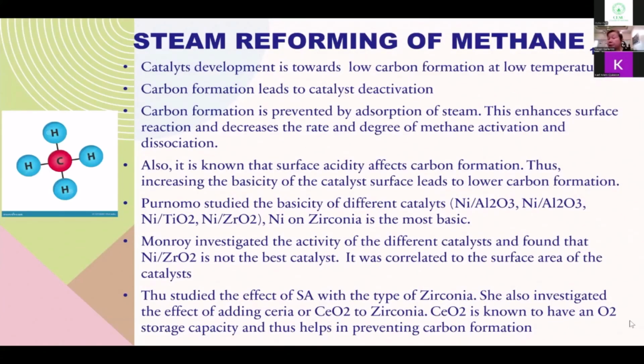The reason for this can be interpreted in terms of surface area. The zirconia used had the smallest surface area compared with the others. It is known that the catalytic activity has a linear relationship with surface area. Because of high operation temperature, the catalyst for steam reforming reaction has to have thermal resistance as well. The highest surface area may not exhibit the highest catalytic activity.